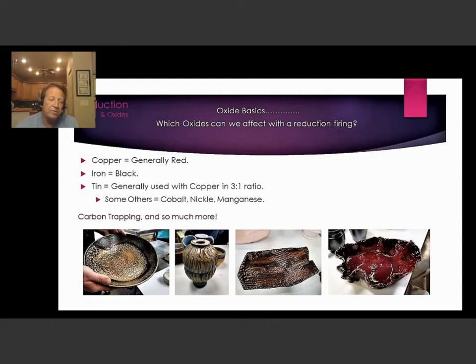So if you look below on the left, we've got carbon trapping in Shino, and that is a reduction, something fired in a reduction environment. That's how you get that look. The vessel to the right looks great, but you're saying, well, it's kind of ordinary. But if you notice, there's really nice iron highlights in there, and guess what? When you oxidize iron, put it in oxidation firing, it's kind of a refractory. When you take that same iron and you reduce it, it becomes a flux. So now you've got extra movement in your glazes.